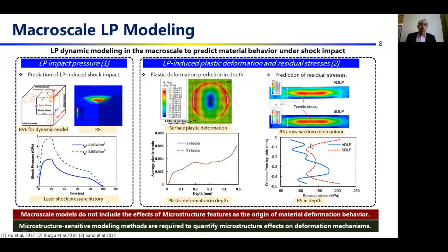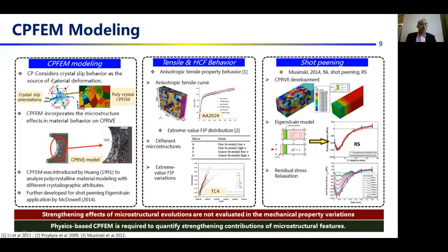However, macro models do not include the effects of microstructural features as the origin of material deformation behavior. For this purpose, microstructure sensitive modeling methods are required to quantify the microstructure effects on the deformation mechanism. The CP model, crystal plasticity model, considers the crystal slip behavior as the source of material deformation, and CPFEM incorporates the microstructural features in the material modeling, such as grain texture, crystal morphologies. This method has been developed to predict the microstructure sensitive material tensile behavior and variations in the fatigue properties.